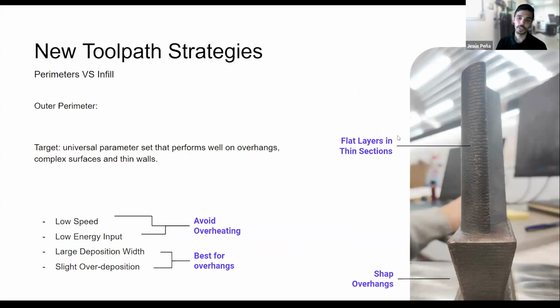And directly in our software, we have strategies for knowing exactly where I can have an overheat, so the part is just going to wait for a few seconds, not to overheat the area, what energy density I'm using, do I need to use a utility profile, do I need to use a fully dense profile, how long this print is going to last, how much gas I'm going to consume, material, what is going to be my cost. Optimizing those toolpaths, optimizing the knowledge that we have inside the software for every application and every print is going to lead to getting the proper mechanical properties, the ones you are in search of.